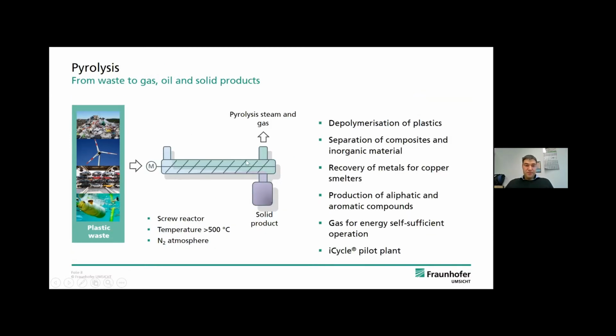So at Fraunhofer UMSICHT, we are working with pyrolysis. And we there have a screw reactor, and the screw reactor is filled with different kinds of plastic waste. So we are experimenting with lots of plastic waste like sorting residues. We also have carbon-reinforced or glass-reinforced plastic waste, shredder residue from the electronic or automotive industry, but plastic waste in general. The material goes into our reactor via a chamber system, and the atmosphere is replaced with nitrogen, and we have temperatures above 500 degrees.